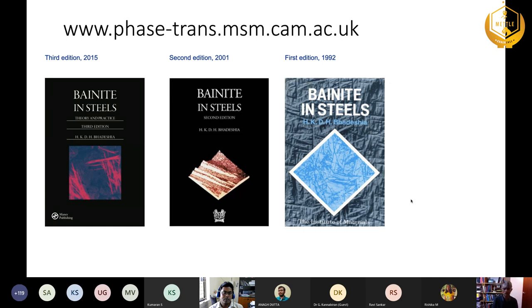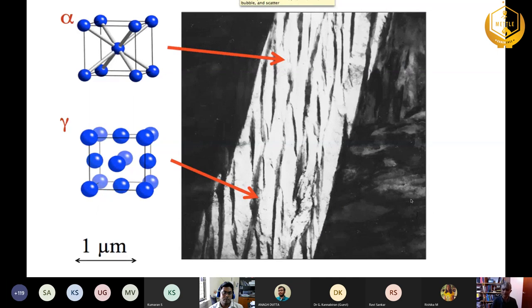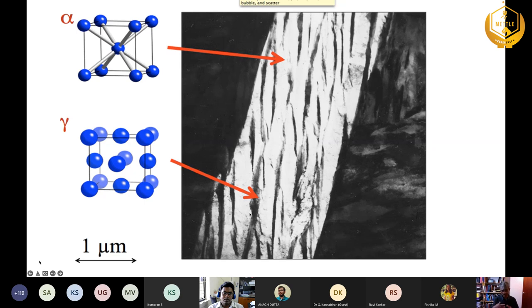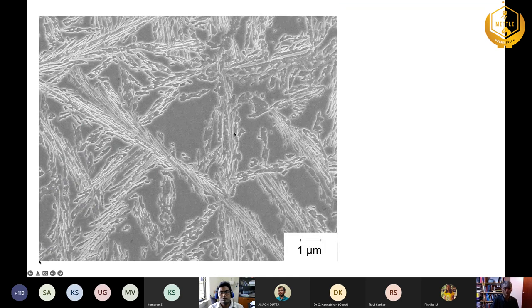Just to illustrate what bainite is: here is a transmission electron micrograph of a collection of bainite plates. The individual plates are about a quarter of a micrometer in thickness and are separated by films of austenite. This is like a natural composite with very fine crystals of bainitic ferrite separated by thin films of austenite, which help to improve the overall mechanical properties. If I look at this using an optical microscope, you'll see that in addition to these thin films of austenite you also have large blocks of austenite between those collections of plates. On an optical scale it's not possible to resolve the individual plates.